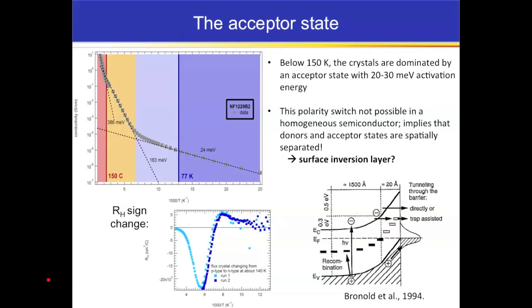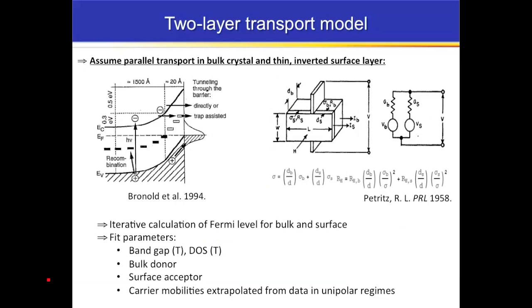This is impossible to understand for a homogeneous semiconductor. A normal semiconductor should show a monotonic increase or change in the Hall coefficient when you're out of the intrinsic region. In order to explain a change in the Hall coefficient when you're not in the intrinsic region, you have to invoke the idea that you've got an inhomogeneous semiconductor or a change in charge transport mechanism, so that your Hall data is no longer telling you anything relevant. We don't believe that the charge transport mechanism changes to something like variable range hopping. What we believe is that this change is indicative of a surface inversion region that's hole type, that's hole-rich.